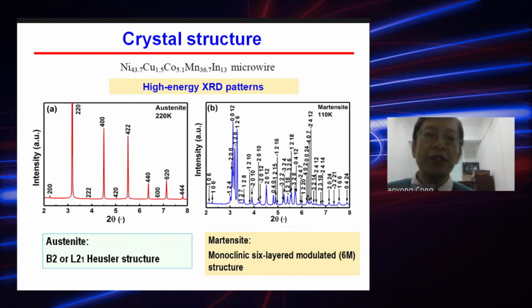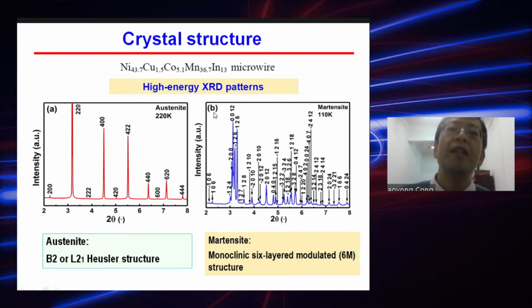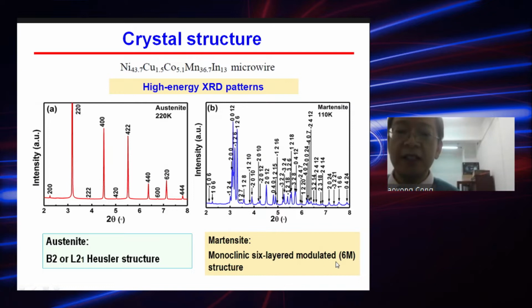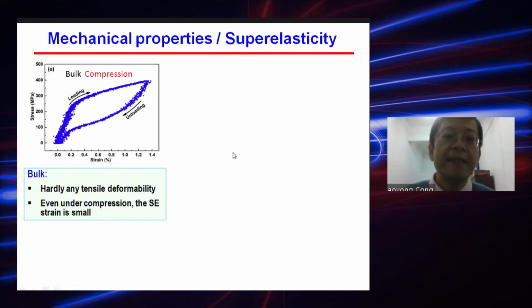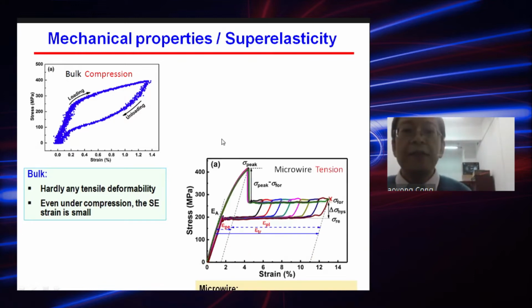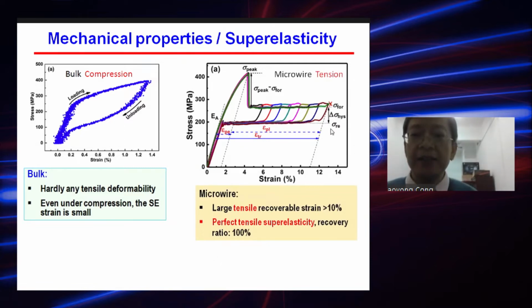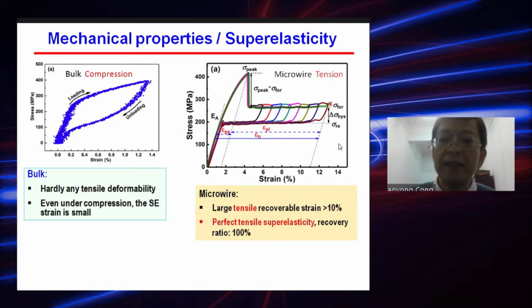First, we studied the crystal structure at both high temperature and low temperature by X-ray diffraction experiment. We find that the austenite has a B2 or L2_1 Heusler structure, and the martensite has a monoclinic 6-layered modulated structure. Then we investigated the mechanical properties and superelasticity. We know that for the bulk polycrystals of magnetic shape memory alloys, it shows hardly any tensile deformability. Even for compression, the superelastic strain is usually small, about 1%. But for the microwire, we get very large tensile superelasticity. The recovered strain can be more than 10%. And also, the strain can be fully recovered after unloading, giving rise to a perfect tensile superelasticity.